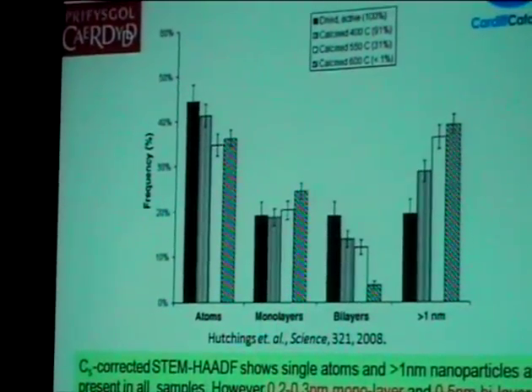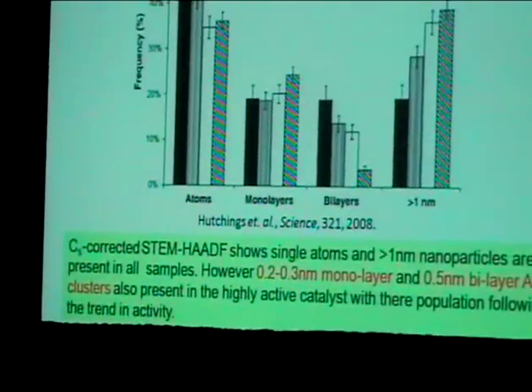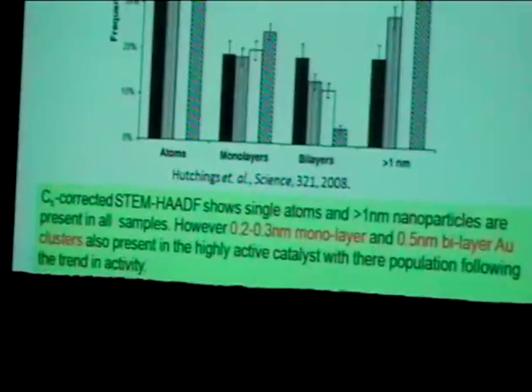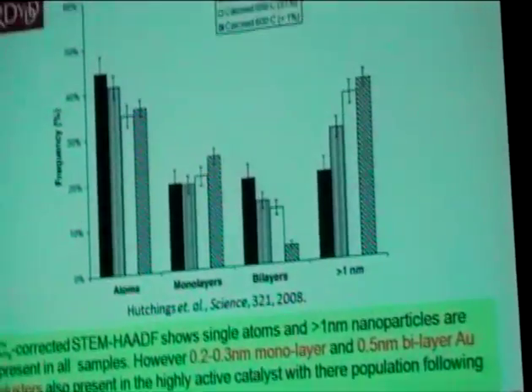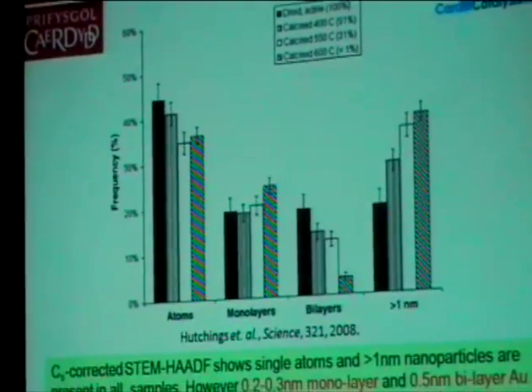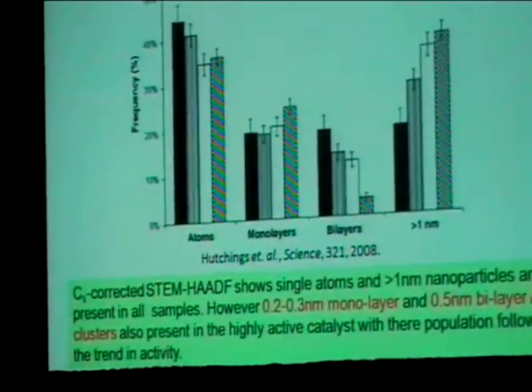If we assume that all of the catalysis comes from these gold bilayers, we get a turnover frequency which is in very good agreement with the model studies by Wayne Goodman on monolayer and bilayer structures of gold. So this led us to propose that these small bilayer clusters could be the active gold species in CO oxidation. And this is work that is still carrying on today in collaboration with Professor Haruta to try and definitively prove this.